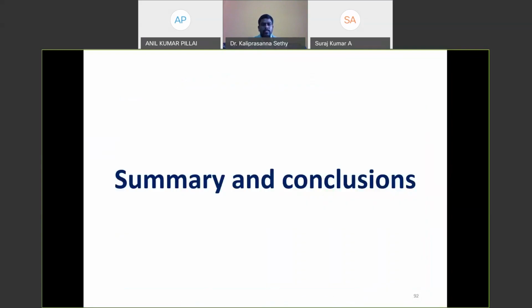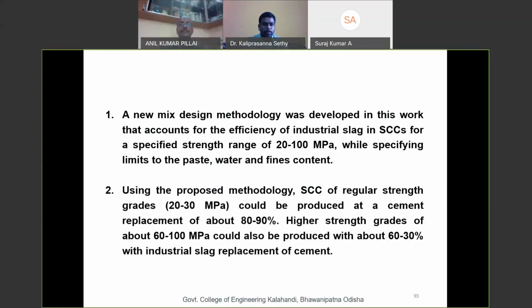And this is the summary based on the work conducted in our laboratory. We can conclude with some of these points. A new mix design methodology was developed in this project that accounts for the efficiency of industrial slag in self-compacting concrete for a specified range, that is 20 to 100 MPa, while specifying limits to the paste, water and fine contents.